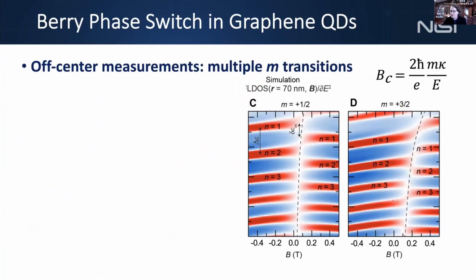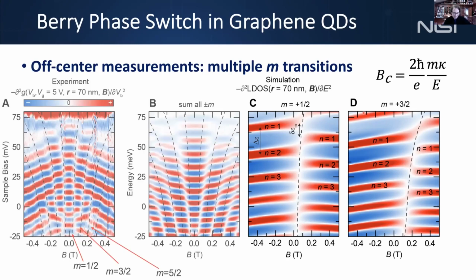So now the other prediction of this critical field is that it should depend on the angular momentum number, m. With higher m values, the critical field should be higher, as shown in these simulations by Levitov's group. And so we can look for that by doing that same measurement I showed you at the beginning, but now parking the tip off center. And that's shown here at the left. And you can see many jumps now.